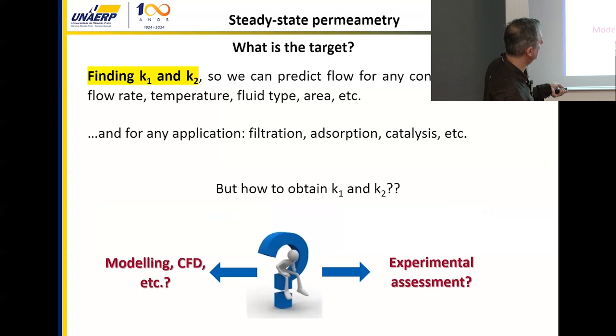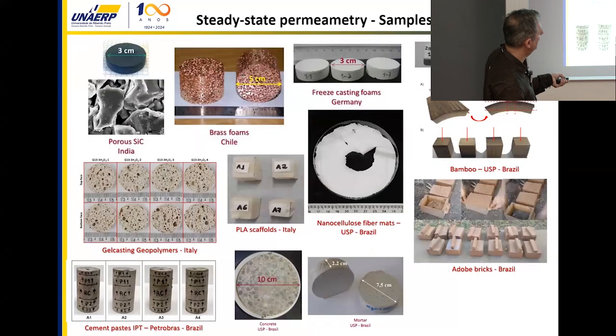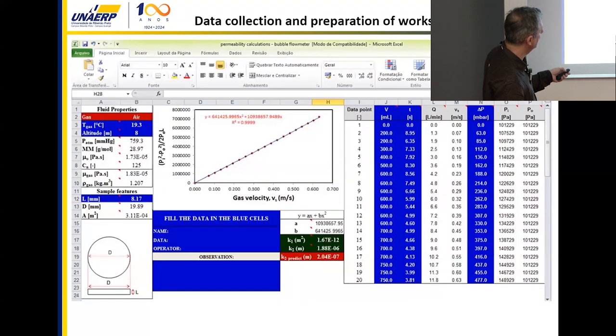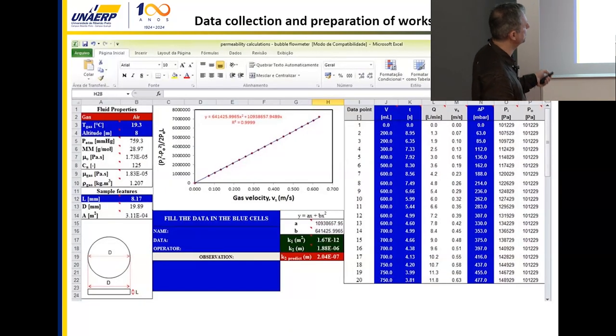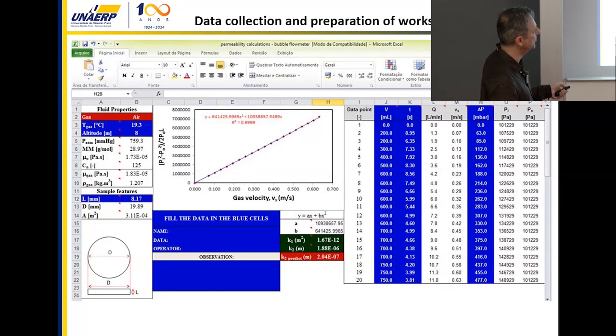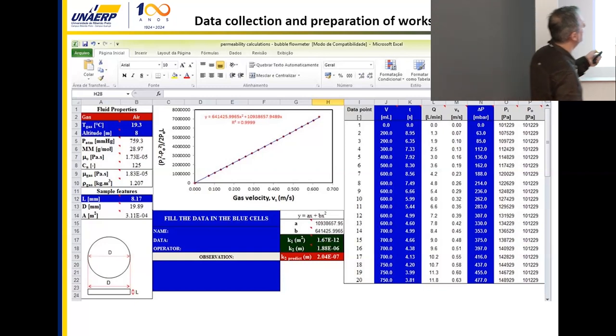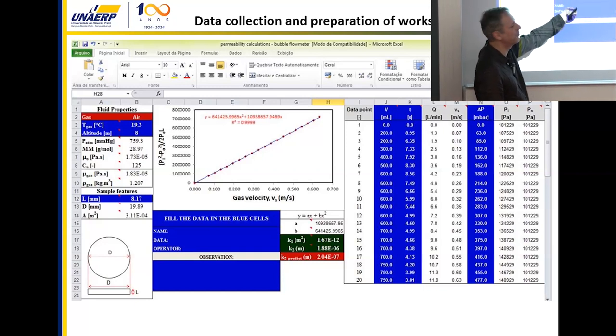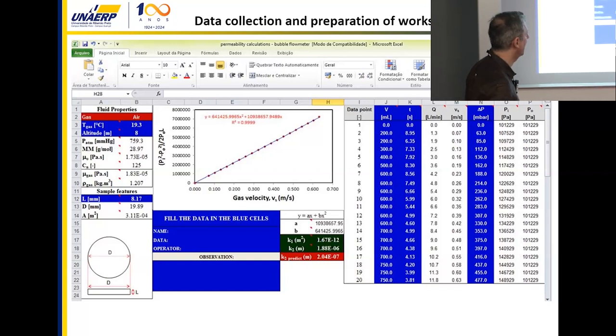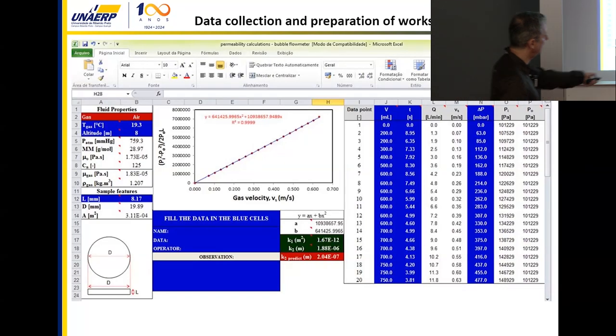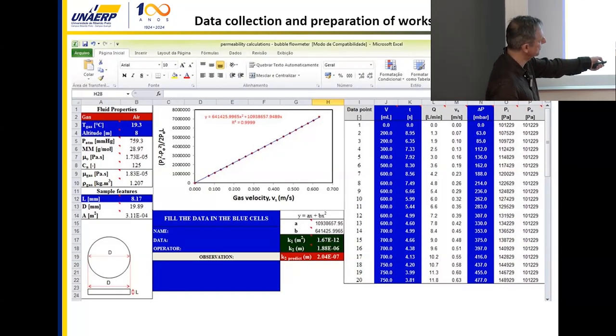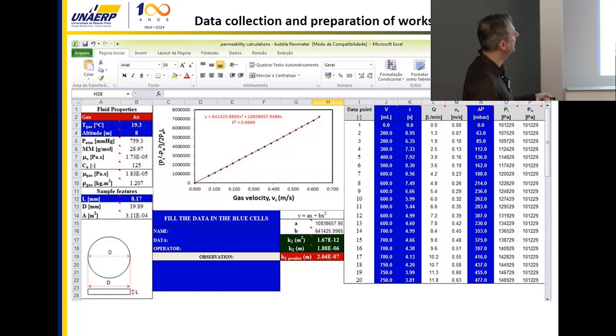This is okay. Here, experimental, different types of materials. This is the worksheet, the Excel sheet that you use to collect the data: volume, time, or directly the flow rate, depending on the range, and the pressure drop, then you can fit. You see here that it looks like a straight line, but if you fit a parabolic curve, you have a much more reliable fitting. So here we have the two constants or coefficients, K1 and K2.